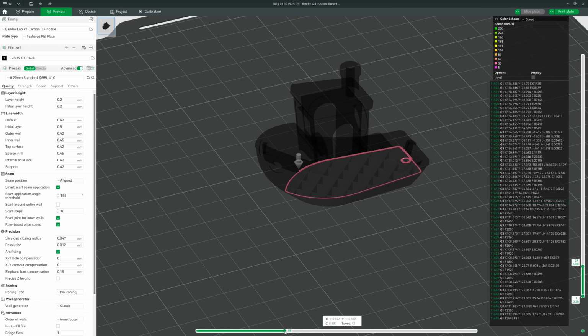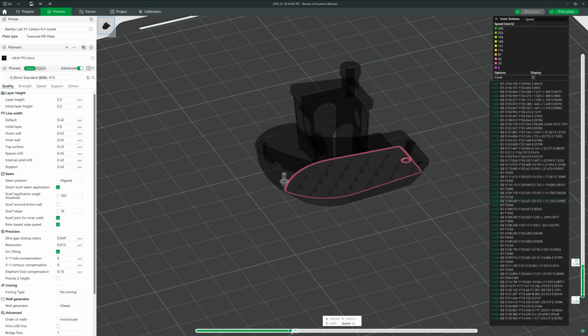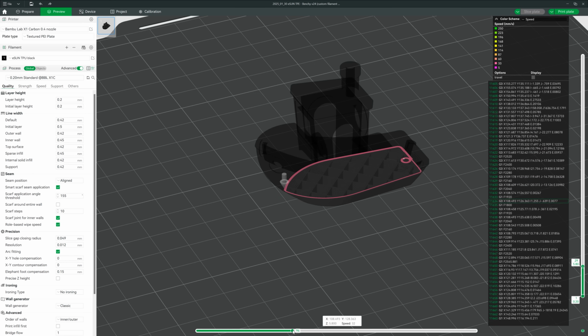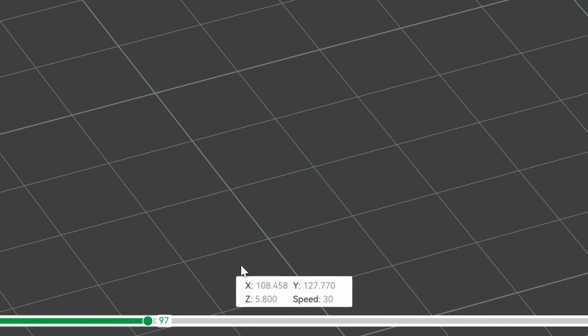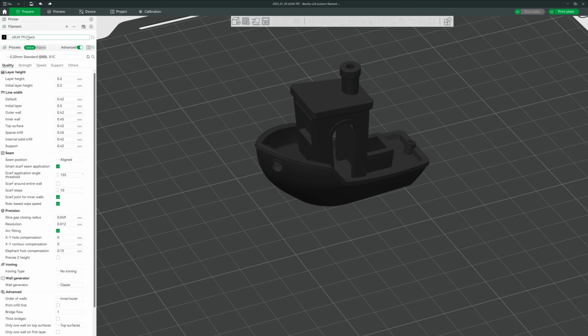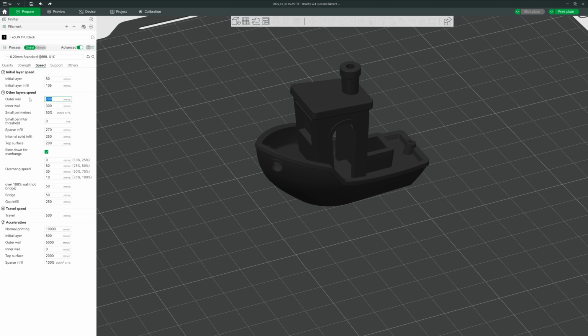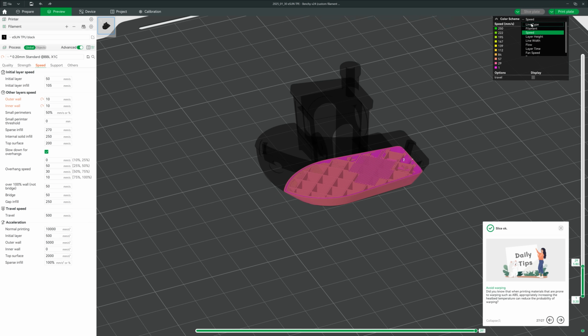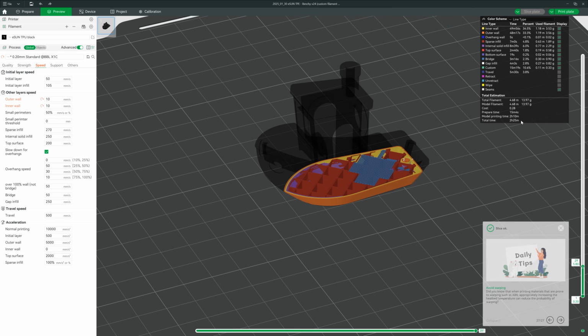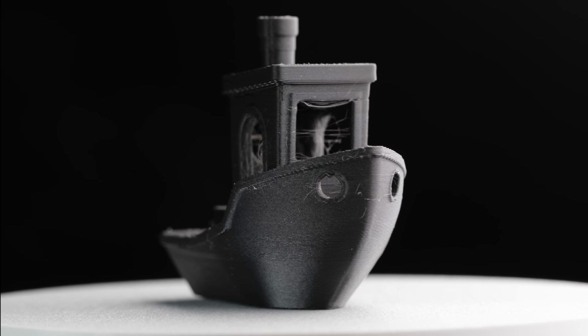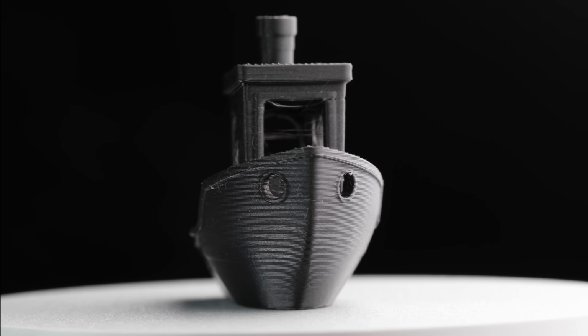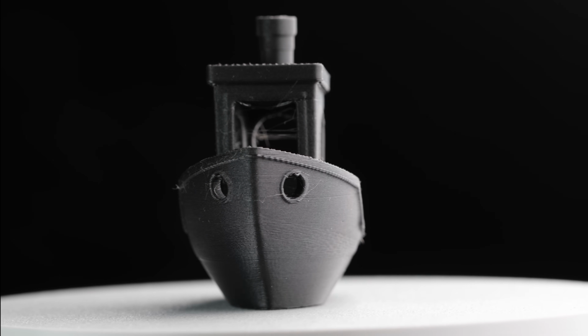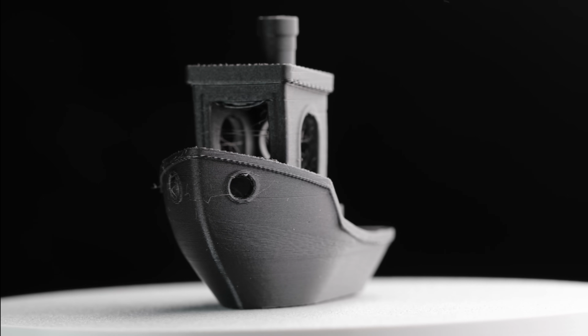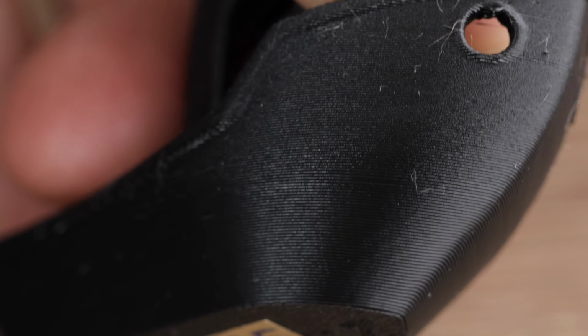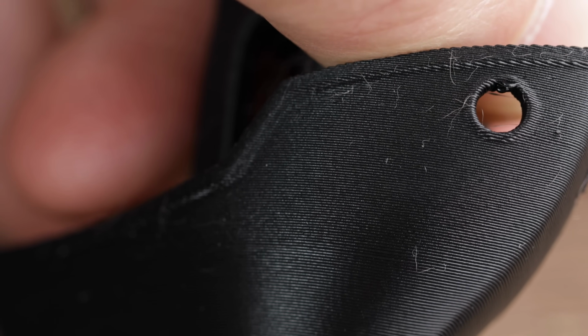In the slicer preview, using color scheme speed, we can check the print speed in this area. It's 30 mm per second. Alright, time for Benchy number 4. This time I reduced the inner and outer wall speeds to 10 mm per second. Print time 2 hours and 25 minutes. Now let's analyze the results, because we see some very interesting things. The bow is now flawless, but look at the surface. The lower part is glossy, while the upper part has a matte finish.